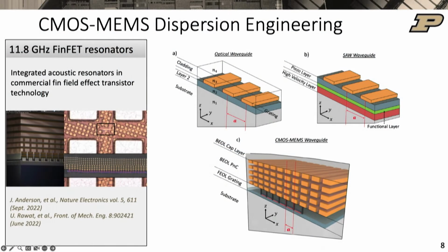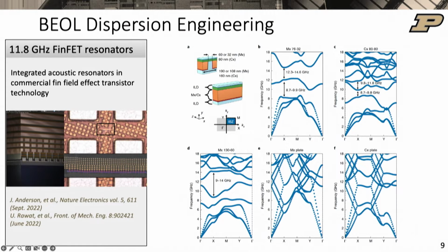And you see we have this periodic structure because that's what we can play with in the back end of line. So we have this phononic crystal waveguide that's generated to create these slow wave structures, essentially, that prevent vibrations up or down. So engineering that's actually really, really challenging because, again, we don't have any control over the number of layers, the thicknesses of each layer, and there are limitations we have to work with within the constraints of the foundry, design rule constraints or DRC constraints, if any of you have ever taped out in a CMOS chip.